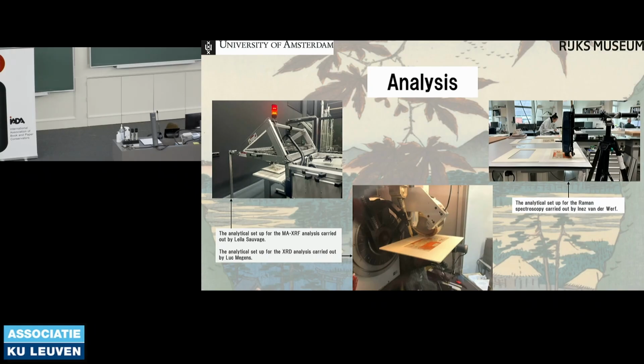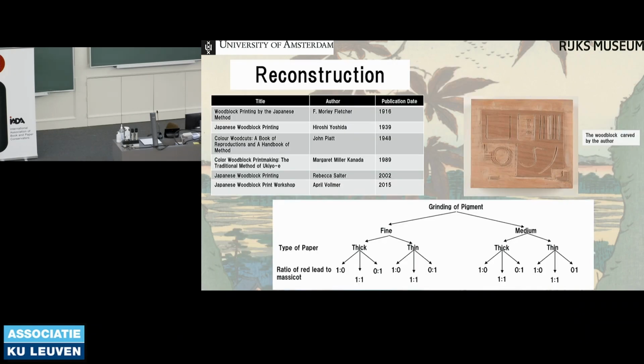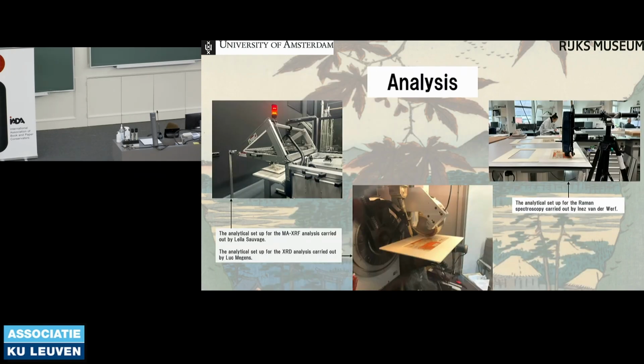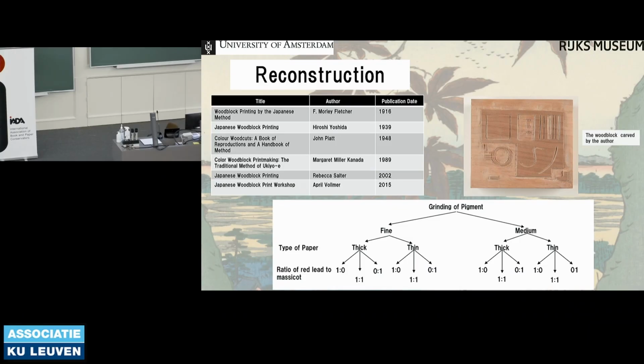First, I worked with Luc Megens to test out X-ray diffraction, and I also worked with Inez van der Werf to test out Raman spectroscopy. Sadly, both these methods did not identify the discoloration. And then finally, I also carried out microscopy myself on both the examined prints, on the Rijksmuseum's prints and the reconstructed samples I made.